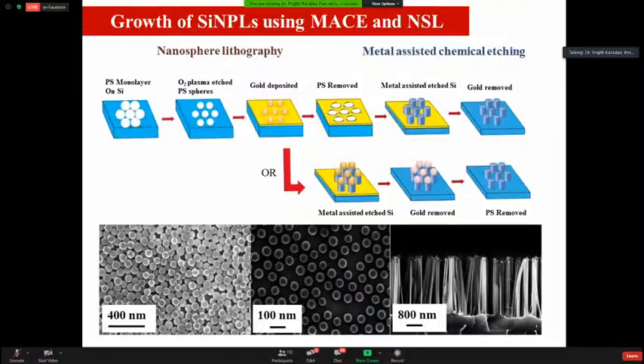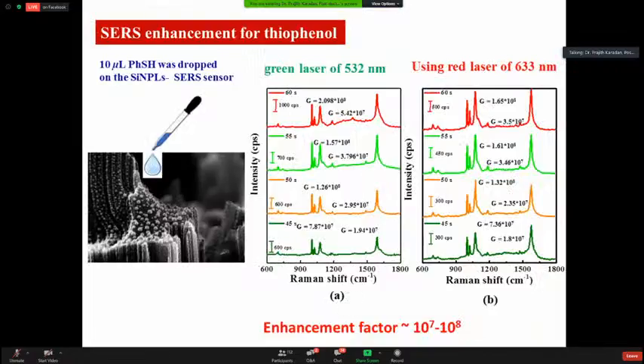So here we have the SEM images of the polystyrene nanospheres coated on top of the silicon substrate. Then the separated polystyrene nanospheres using oxygen plasma etching. Then we have the cross-sectional image of the silicon nanopillars. So after making the silicon nanopillars, we have decorated them with silver nanoparticles. So these silver nanoparticles possess the plasmonic capabilities.